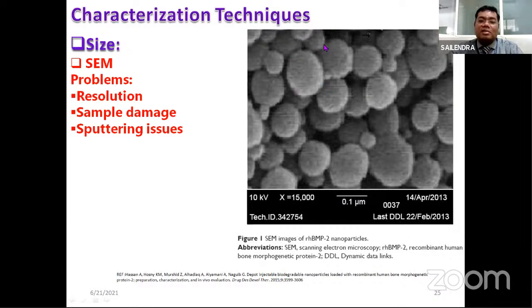You have to coat these nanoparticles with certain conductive particles, so that whenever the charge is thrown on it, the charge dissipates very nicely through this conductive particle and you get a very nice image. So if you sputter the surface of the nanoparticles with an element for, suppose, 40 seconds, 50 seconds, the coating will be so thick that you cannot find the edges properly. So sputtering time is also very, very important when you are analyzing these scanning electron microscope images for size. If you have too much sputtering time, you will lose the edges of these nanoparticles, and the extra sputtering will be deposited in between the grooves of the nanoparticle, and you won't get a perfect size from a scanning electron microscope.